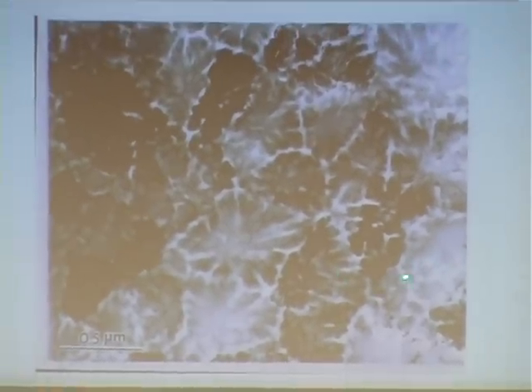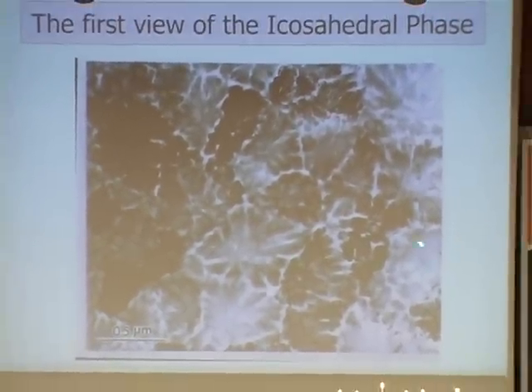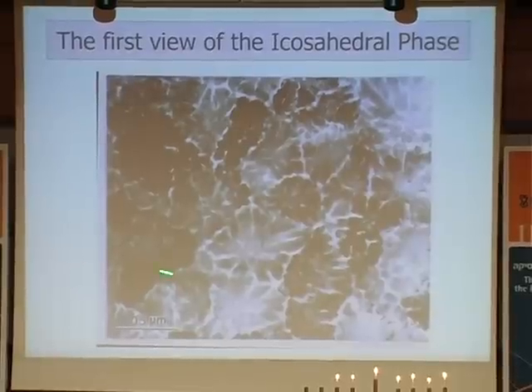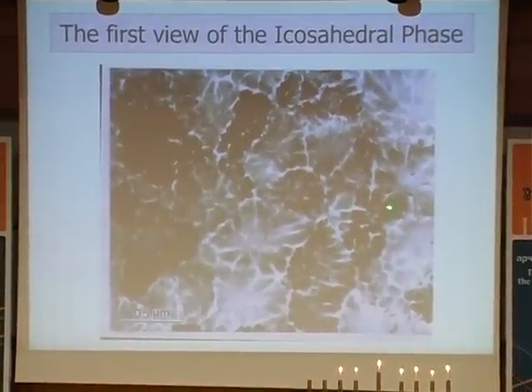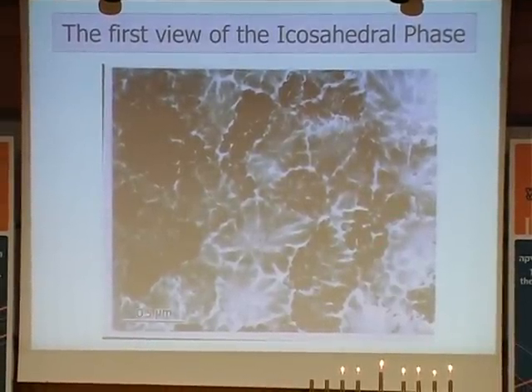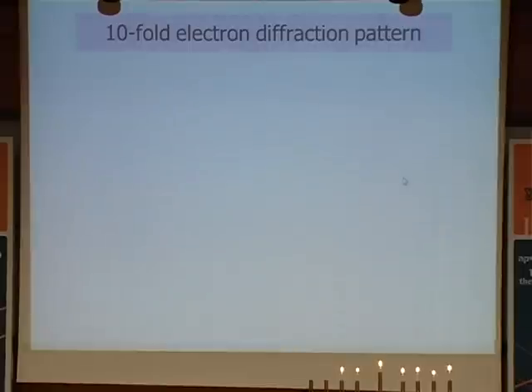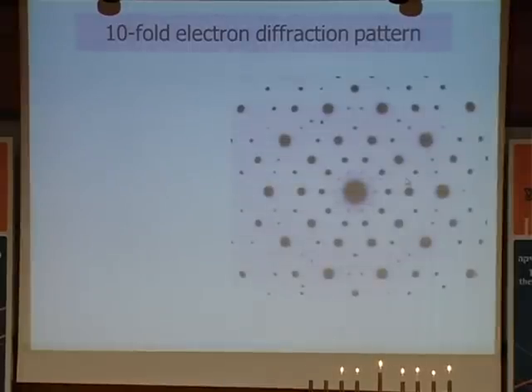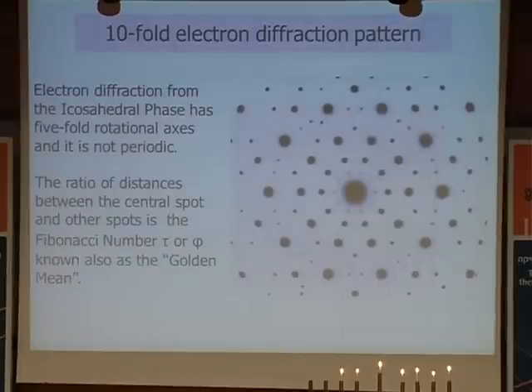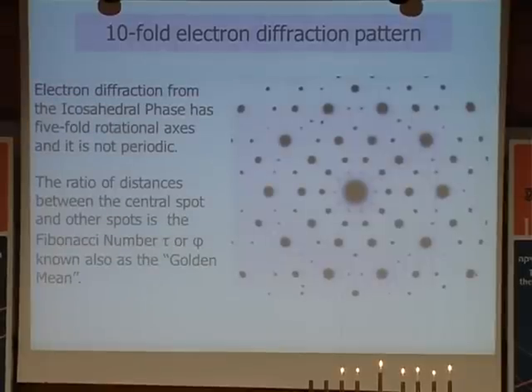And as you can see here, some of them are very, very black, very dark. This here and this here. While others, these are transparent, more or less. Right? This is normal view, but that's very abnormal, dark like this, heavily diffracting. And this was the electron diffraction. So when I saw this electron diffraction, I remember very well. I was sitting there and saying, wow, that's very odd.